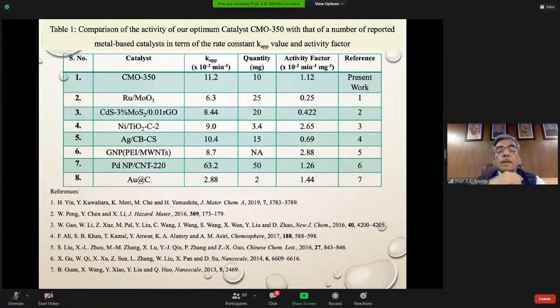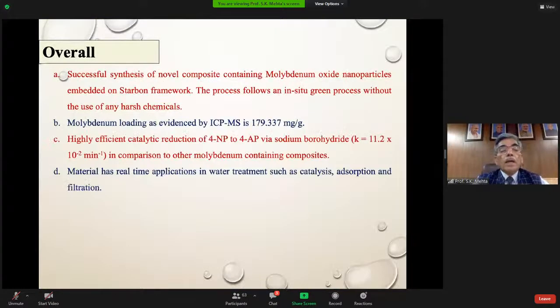Our rate constant was good. And the palladium one is not a green approach, but we find that ours also gives a good rate constant. So this can be acceptable. And overall, I would say that we had a successful synthesis of novel composites containing molybdenum oxide nanoparticles embedded on a starbon framework. The process follows an in situ green process without the use of any harmful chemicals.